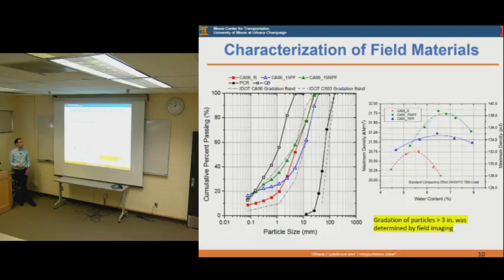This is the gradation of all the materials that were used in cell 1. Essentially, we did the moisture density characterization because when we constructed the test sections, we constructed everything and compacted it at the optimal moisture content in order to get high relative compaction. And as you see in the gradations, these are the large aggregates, an open graded material with very large sizes, and then the quarry byproduct is the finest gradation, while the other 3 materials fall within the gradation band for the CA6 of IDOT, shown here with the dashed lines, and 2 of them have a higher fines content than the currently permitted 12% fines content.